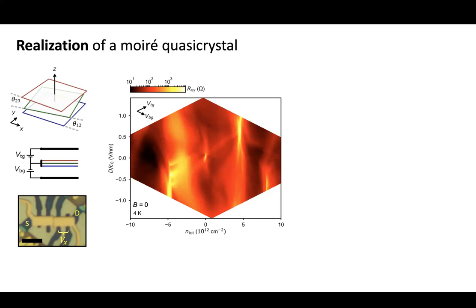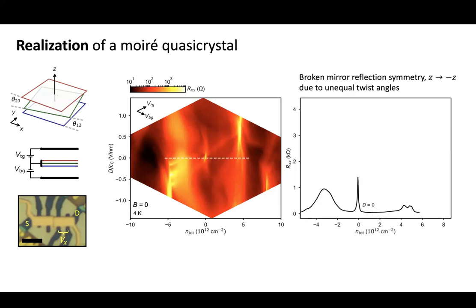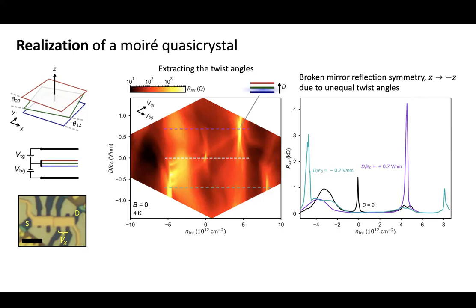However, we can still extract the twist angles by doing the following trick. You can take a cut here and you can see some peaks. You take cuts at different energies, you see different peaks, and they occur in different regions. So how do we extract the actual twist angles? We choose a displacement field and a density such that we're exploring the band insulator that would happen if you had only the bottom bilayer. And we tune the top layer to the charge neutrality point, and then we see an enhanced resistance peak. It's not infinite, it's not an insulator, because the top layer still conducts at charge neutrality, but it's a distinct high resistance feature which occurs at a given density. And that tells us that layers one and two have a 1.4 degree twist angle.